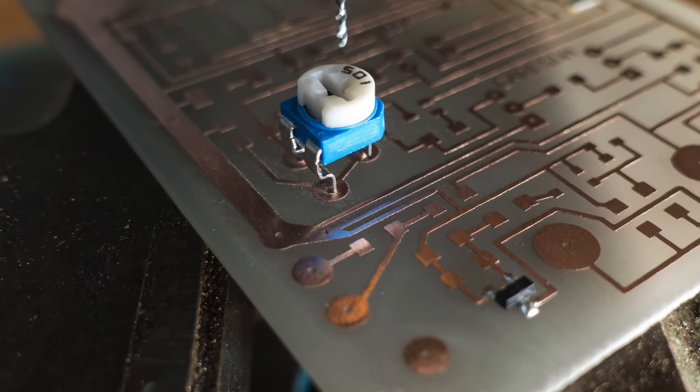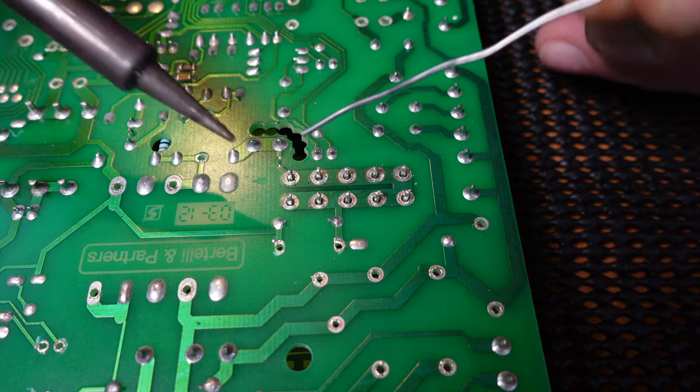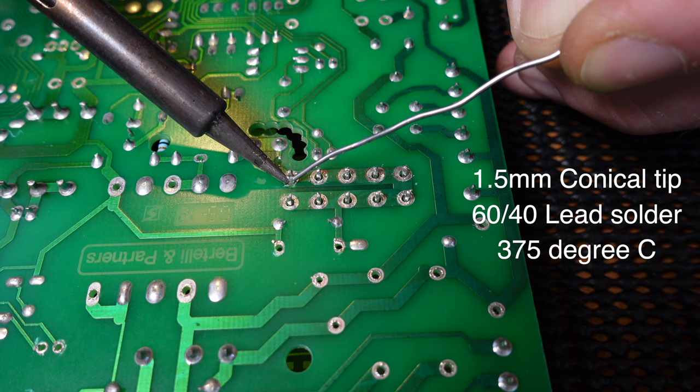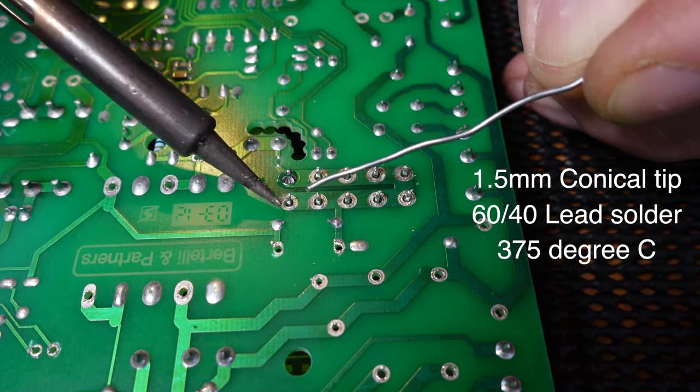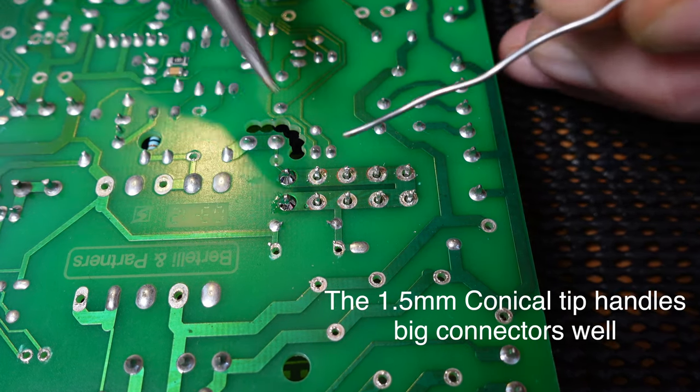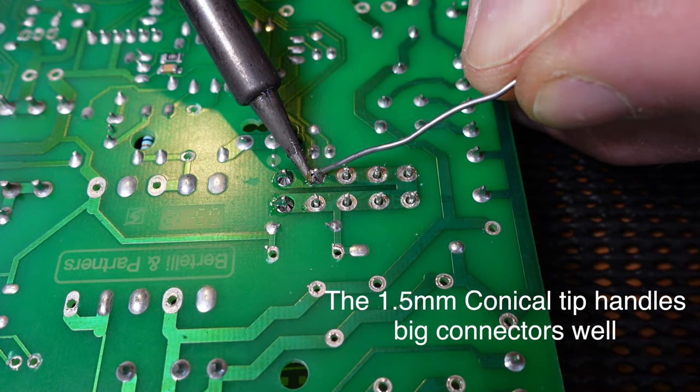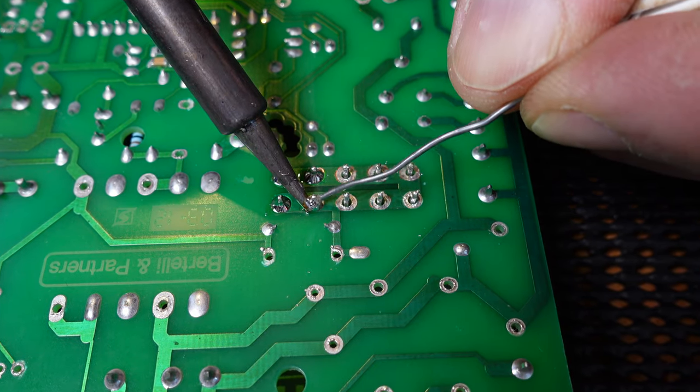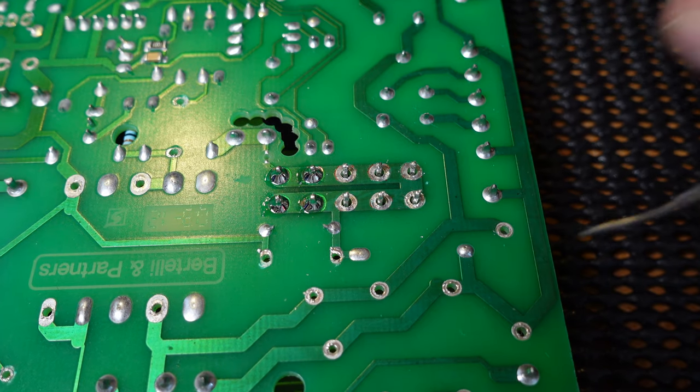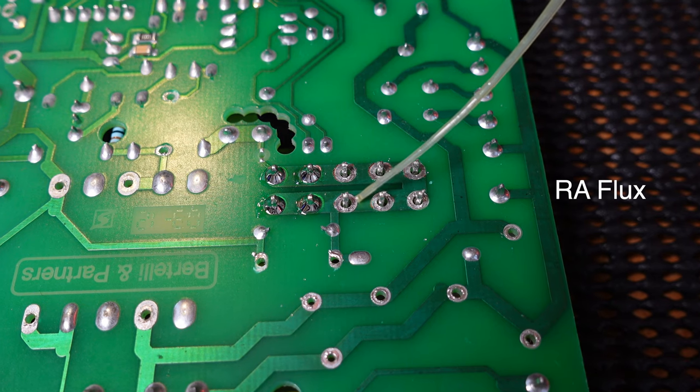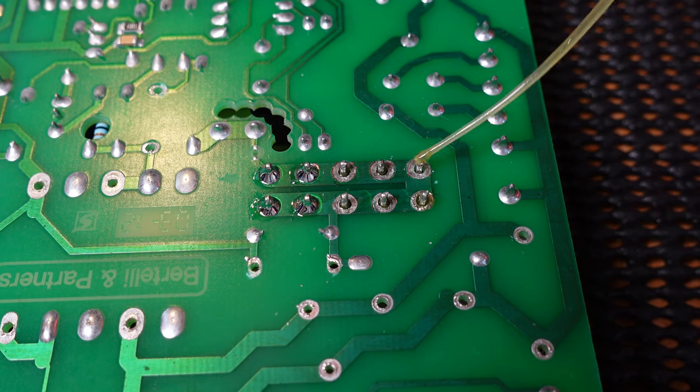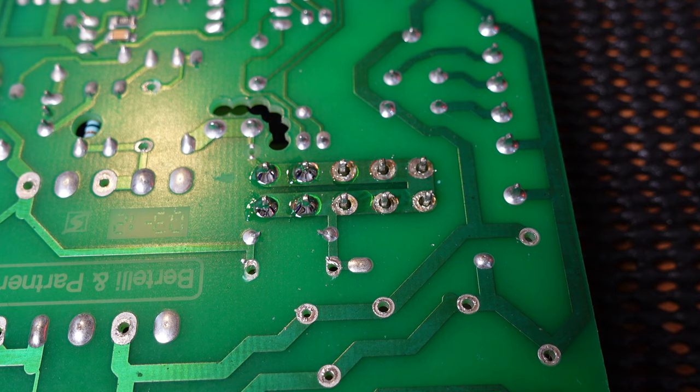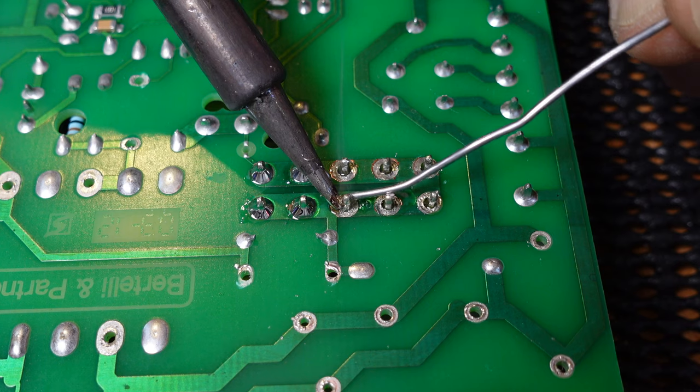Here's an experiment. These are big cable connectors on a duff circuit board. I just wanted to show you how lovely the lead solder flows and the indicator of how shiny it is. In each one of those you can see the joints just spot on. At 375 degrees with that conical 1.5 tip, it does a lovely job even with a big leg like that. Now just for argument's sake, I'm putting some RA flux on. I want to show you that there's absolutely no point in doing this. There's enough flux in the core solder, in the Weller that I use, to do a perfectly good job.